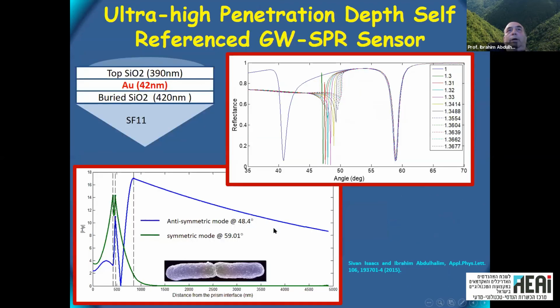And in order to do that, we went to a multi-layer structure, which is similar to the configuration I mentioned for long-range plasmons, where you excite another plasmon on this interface, and you can use it as a reference. But the astonishing thing is that if you add an additional layer here, it acts as a waveguide, but then you can tailor the parameters so that the mode has a very large penetration depth inside the analyte.